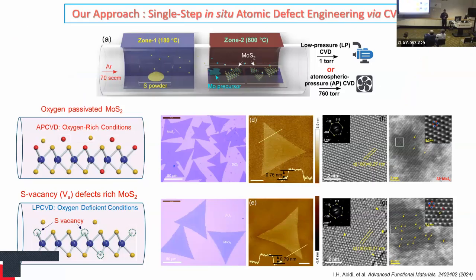In atmospheric pressure CVD, basically you have oxygen in the environment, so that can play a role in the growth. In the second one, I use low pressure CVD, where I remove all the oxygen within the system. So basically it is an oxygen deficient condition in the growth. If you see optically in the top two images, you can see it's very similar, a triangle single crystal of MoS2.